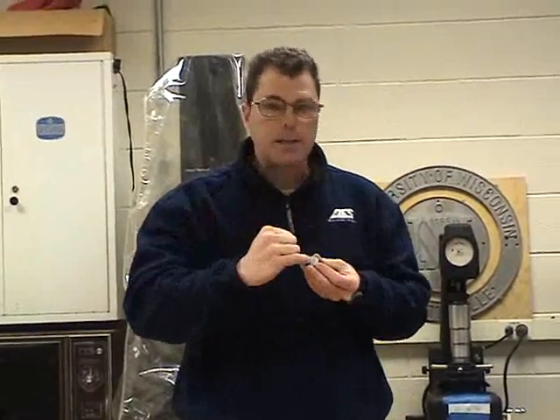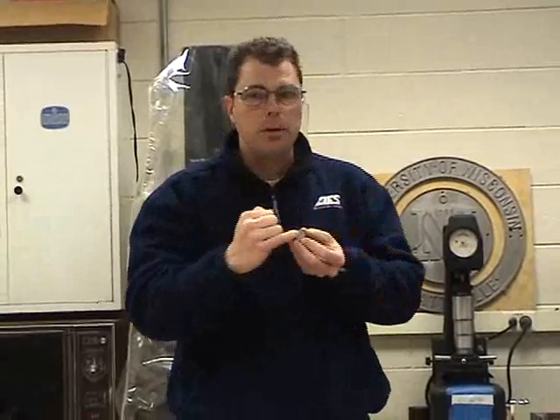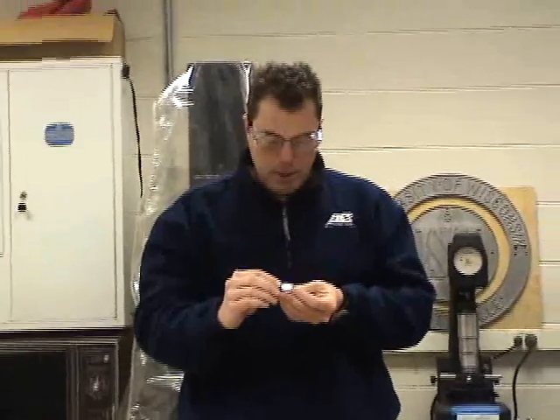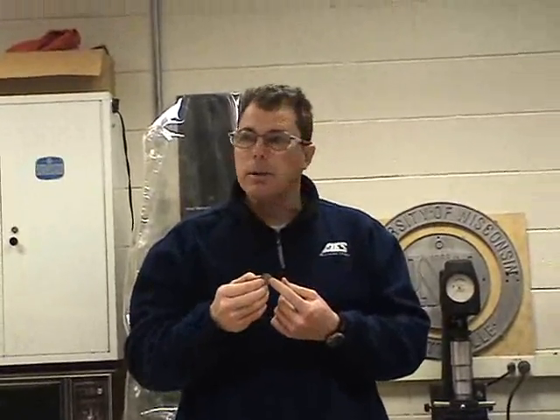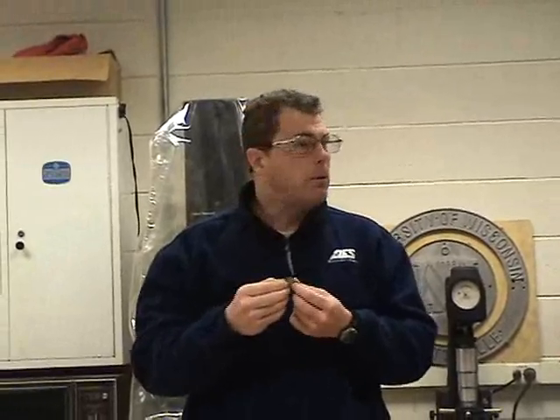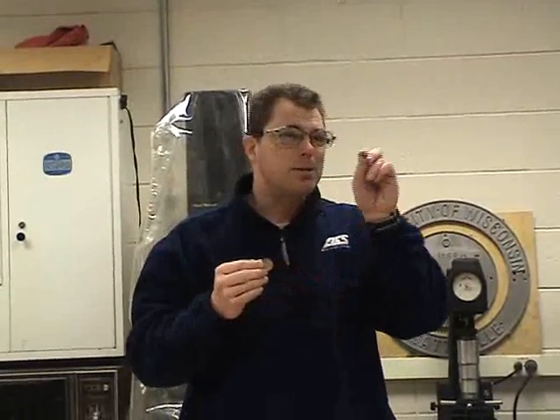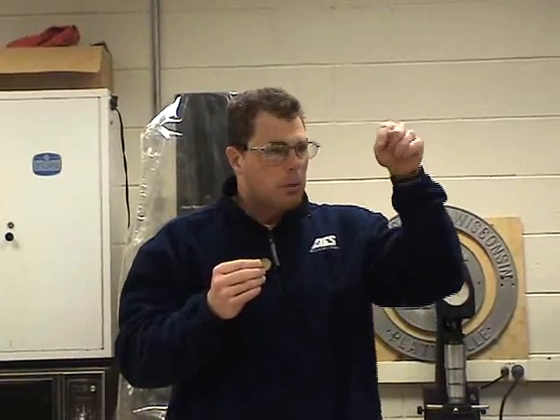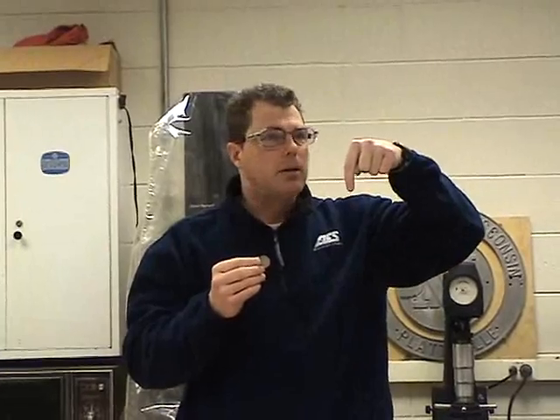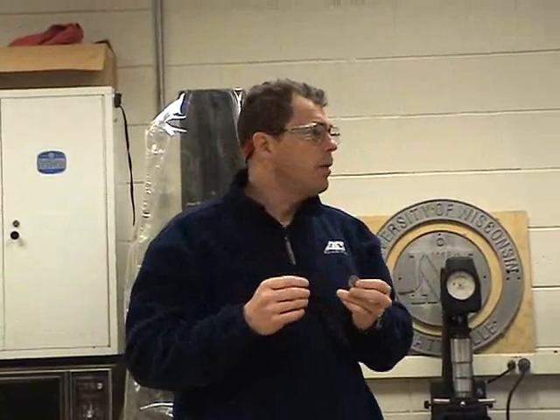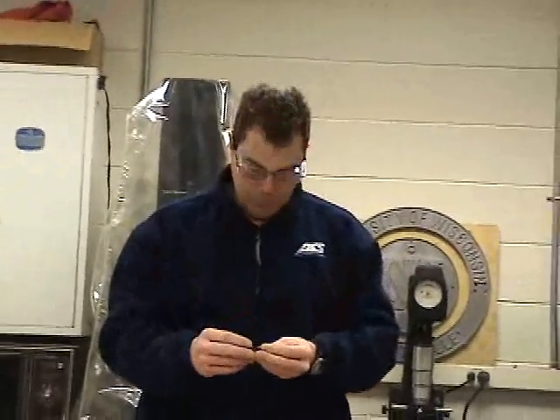The other thing is where it got stamped. You see it's got a number 1 on this one. Where it got stamped, you probably work hardened it a little bit in that area, so you won't want to do a hardness there. You never do a hardness closer than a couple diameters of the indentation away, because when you take a hardness, you're actually plastically deforming the material, and in the area around that, theoretically it's going to get a little bit harder because of the work hardening of the metal.